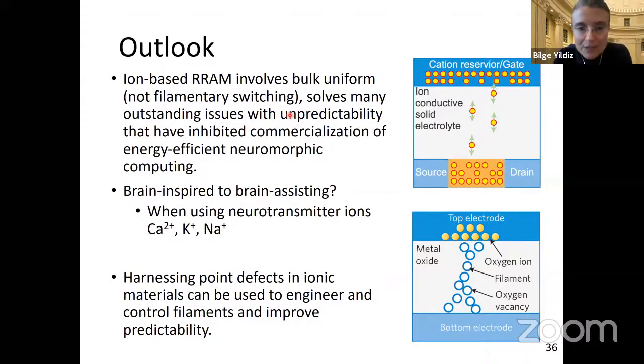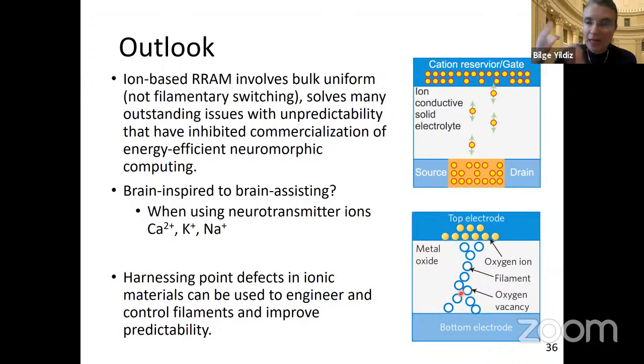Berke asked, what are the differences between microstructure engineering and dopant engineering? So this is related to this last piece on the filamentary devices. Microstructure engineering is to control, for example, the crystallographic texture, grain orientation, grain size, grain boundary distribution. And I say that because extended defects such as grain boundaries or dislocations in such oxides are typically easier to reduce, easier to form oxygen vacancies in. If you start with a very random microstructure, these filaments can form anywhere in any paths with different properties. But if you have a very uniform microstructure, so let's say a well-defined crystallographic orientation, well-defined and a narrow distribution of grain boundary types, then you can actually narrow down the distribution of switching properties.